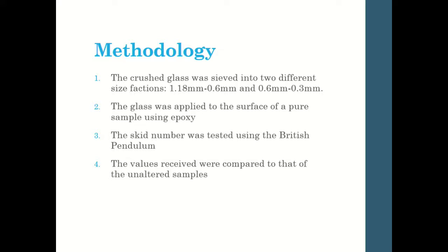What I'm doing is sieving crushed glass into different size fractions. So far I've used two: 1.18 millimeters to 0.6, and 0.6 to 0.3. Once sieved, I apply it to the surface of a pure sample with epoxy, and I use a British pendulum to test the skid resistance of the surface. Once I have those values, I compare the pure to the altered samples, right?